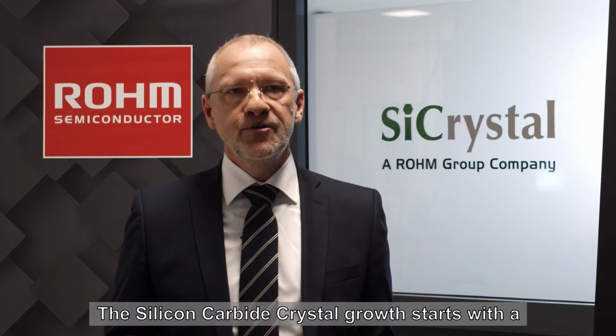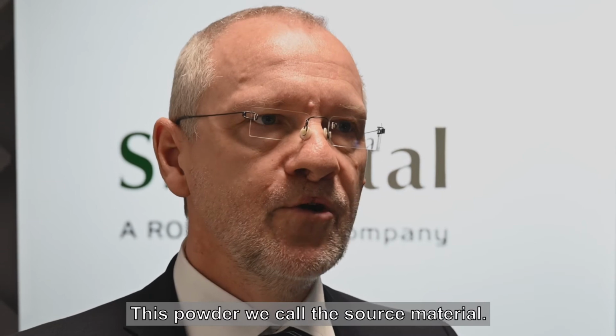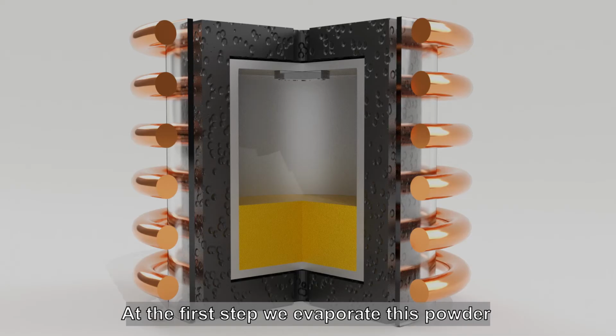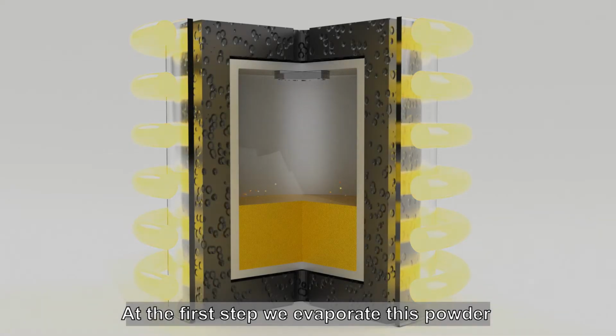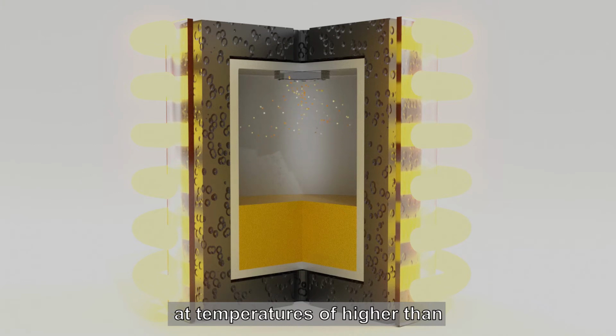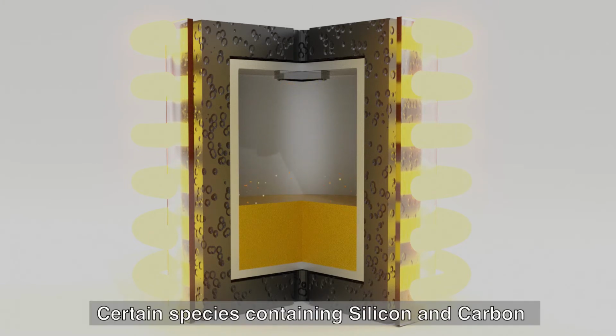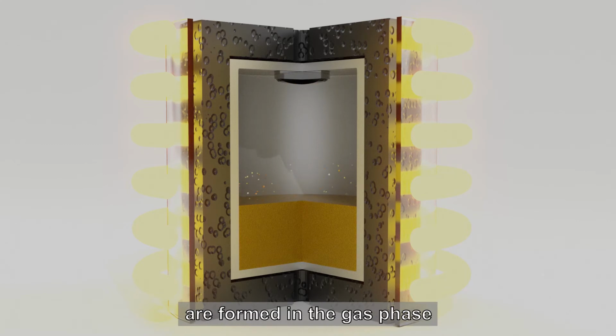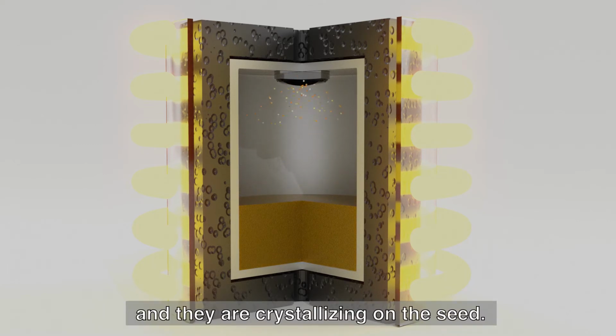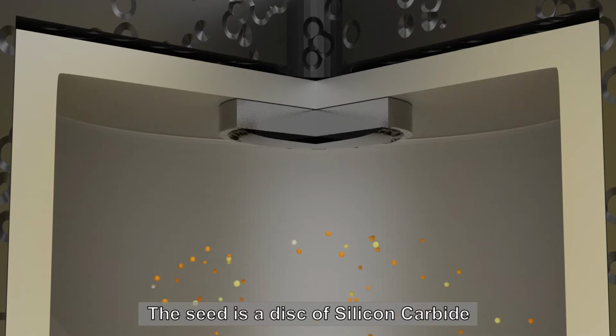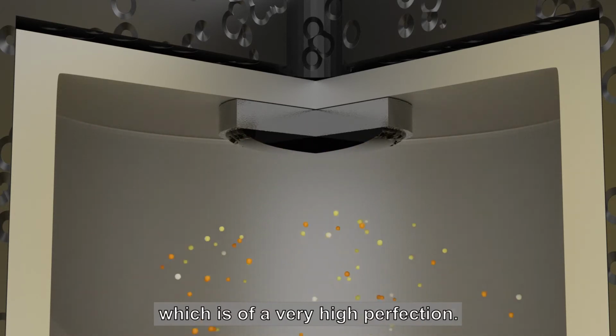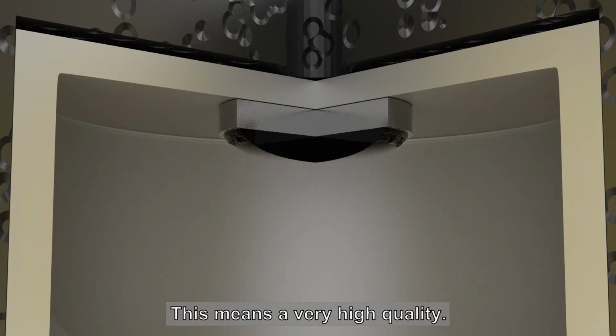The silicon carbide crystal growth starts with a high purity silicon carbide powder. This powder we call the source material. At the first step we evaporate this powder at temperatures of higher than 2000 degrees. Certain species containing silicon and carbon are formed in the gas phase and they are crystallizing on the seed. The seed is a disc of silicon carbide which is of a very high perfection. This means a very high quality.